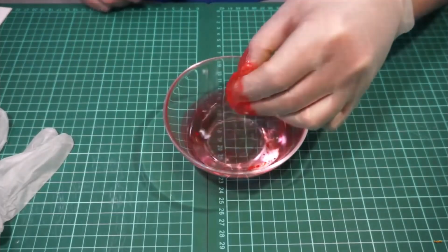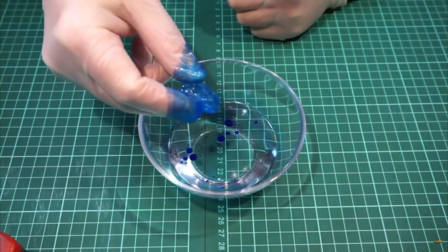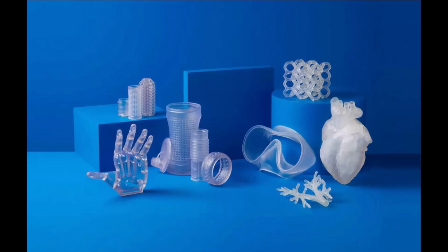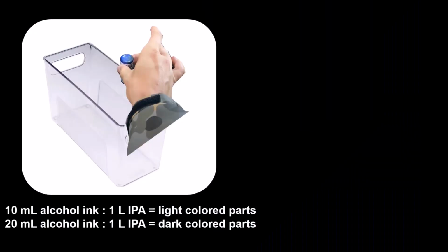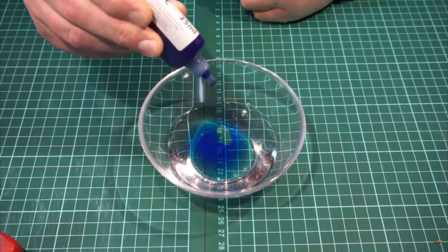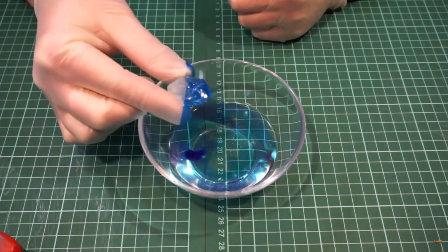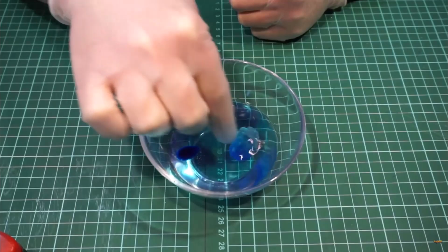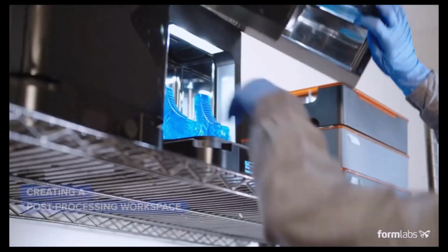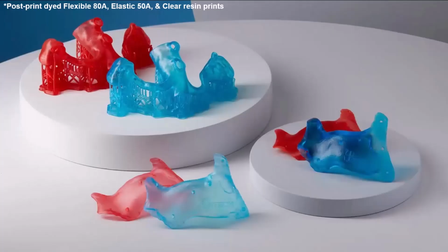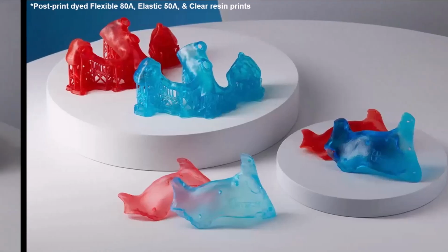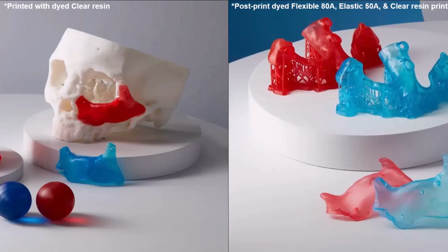The other dyeing method is dyeing after printing. We are not limited to the resin type as before, although this process works best with clear, elastic 50A, and flexible 80A because of their translucency. In this process, we add 10 to 20 milliliters of that same alcohol ink to IPA, depending on your desired color saturation. This can be done in the form wash or in a separate bin. After your part finishes its normal wash cycle, transfer the part into the dyed IPA solution for 10 minutes. The rest of the process resumes normally with curing and so on. And here is the finished result for this method. You can see there is not much difference in the color saturation between parts dyed before or after printing. So it's probably best to dye after printing if you can, to avoid print failures and warranty issues.